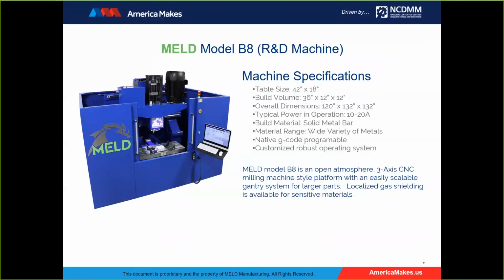Again, we're focusing on two parameters, torque and linear force. We don't have a wide variety of variables that impact the print. So we get consistent results from print to print and from machine to machine because, again, we're using a stable material, which is a solid bar. We're not melting it, so we don't have a lot of challenges with mechanical properties that have a tendency to freak out being a melt base.